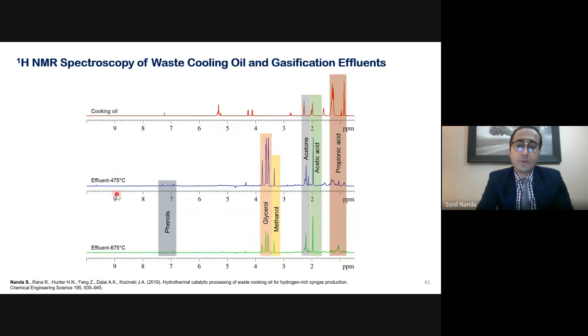Now, the effluent gasification was performed at 475 degrees Celsius and 675 degrees Celsius, and the liquid effluents were collected from the gasification reaction. The effluents collected from 475 degrees Celsius showed increased concentration of acetone, acetic acid, and propionic acid. Whereas when the gasification was performed at high temperature, the concentration of acetone and acetic acid further reduced, and so did the concentration of glycerol and methanol. Now, these components reduced because they were further cracked to produce different permanent gases like hydrogen and methane at high temperatures. One of the factors that showed an increase was the concentration of phenols and phenolic compounds in the effluents at 475 and 675 degrees Celsius.